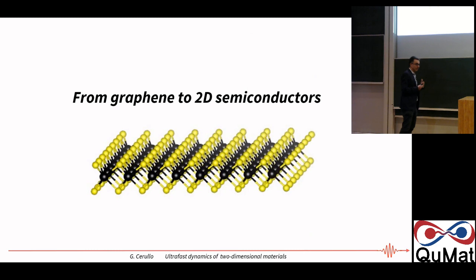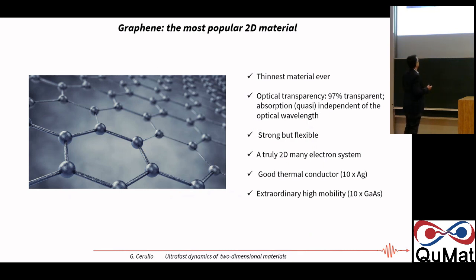So let's start with the introduction on 2D materials. Everything started with graphene, which is really the most popular 2D material. It is essentially a honeycomb lattice of carbon atoms bound by covalent bonds. So it's the thinnest material ever. It's a single layer of carbon atoms, and it has remarkable electronic, mechanical, thermal, and optical properties. And even if it's a single layer, it still absorbs, compared to its thickness, significantly. About 2.3% of the light is absorbed by graphene. So compared to its thickness, the interaction with light is extremely strong.